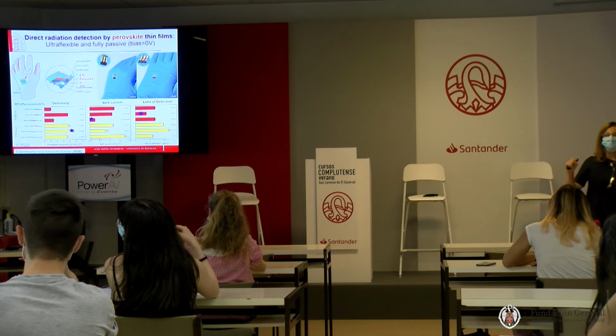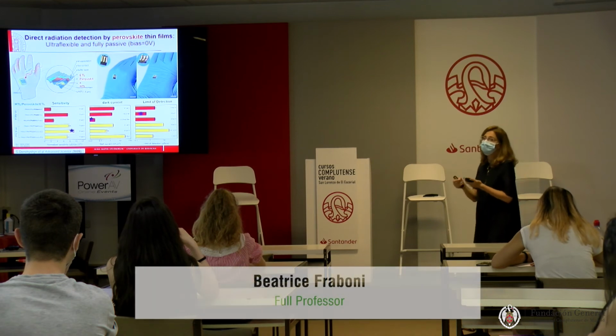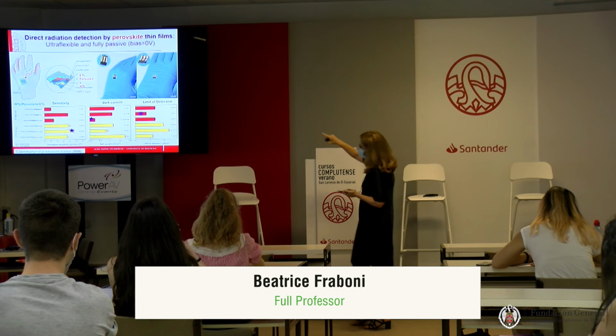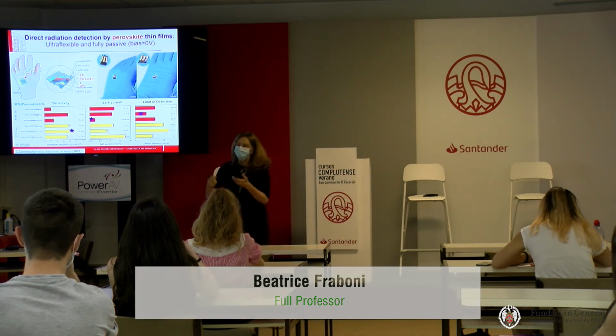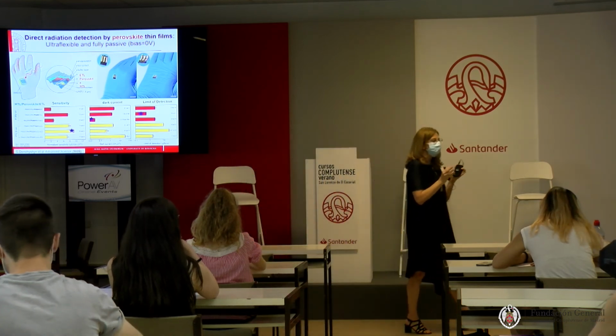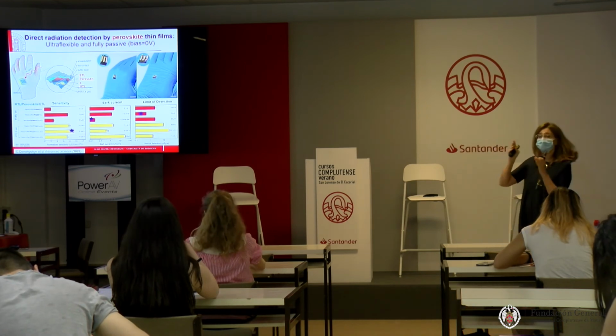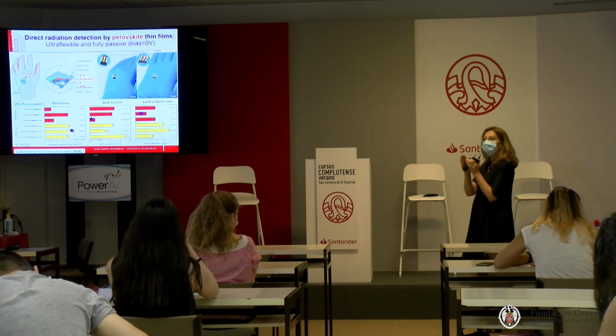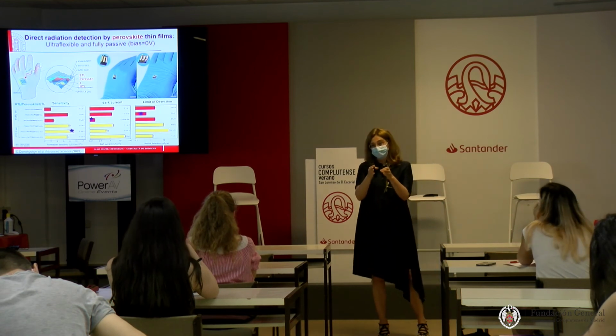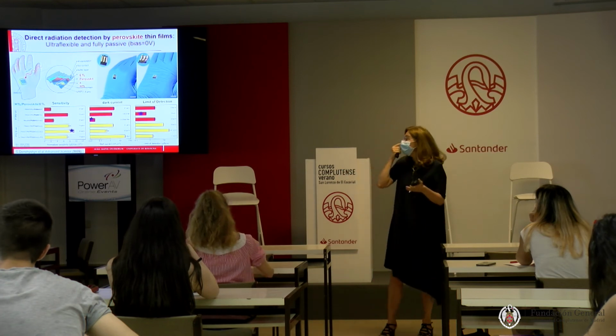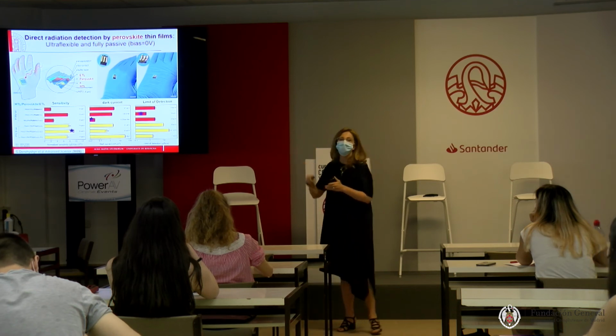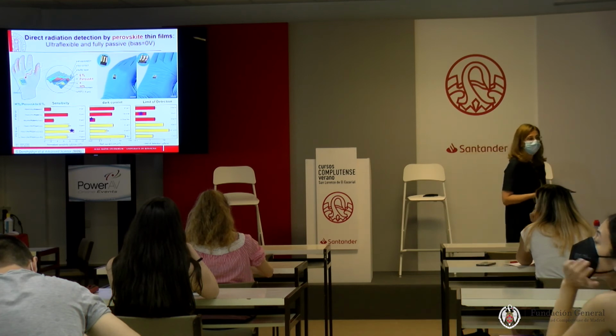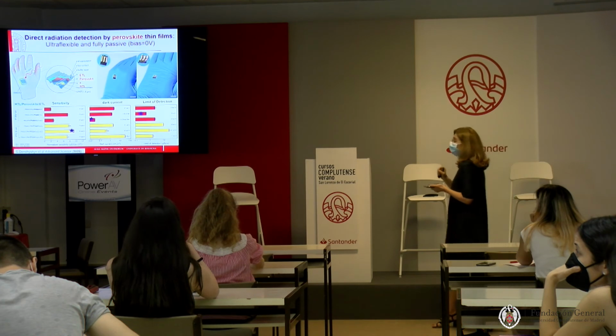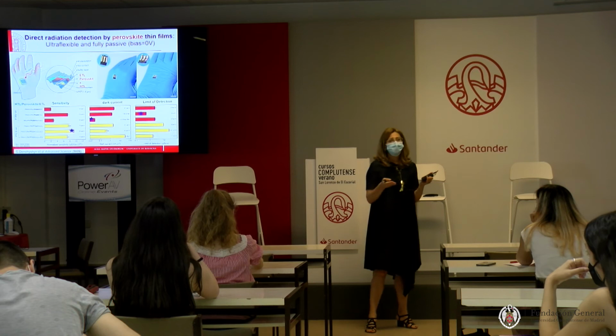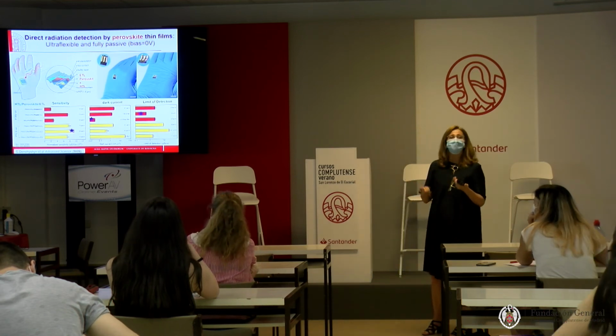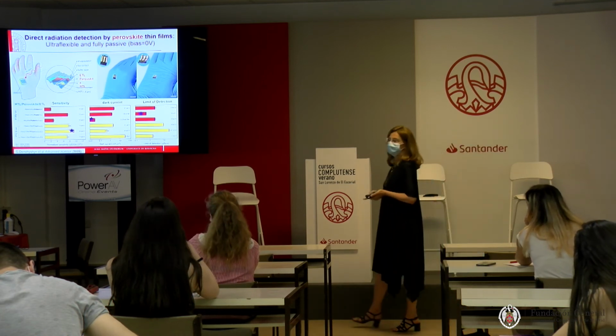Of course, ideally, you want all these parameters to be optimized. But very often, you don't really need all three of them. So what I'm showing here is how, by changing the type of layers that you use to couple to the same perovskite, so I'm using the same active semiconductor but just changing the interlayers that help create the diode structure, the photodiode electric field, and collect the charge carriers, by simply changing their combination, look at how the response and the properties of this device can change. So again, the material is very important, but also the interfaces and the structure of the device that you fabricate have a huge role. And you can play around with them and identify novel and, again, very often unexpected performances.